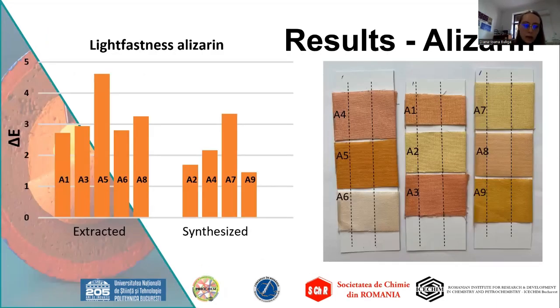The extracted dye as such, which means either synthesized or extracted, but without any nanosol or any other stabilizing agent added, exhibited the best light fastness. And this is valid, of course, only for the used methods. The synthetic ones showed already an improvement with almost 40% better light fastness as compared with sample A1, on the other hand,